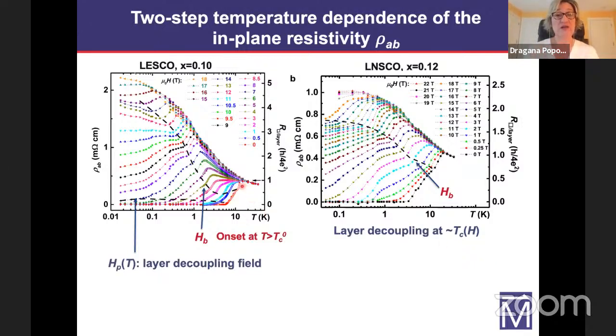Here we are showing curves that correspond to different magnetic fields. Temperature is on a log scale, so you can see the lower temperature behavior better. This dashed line connects these kinks, these initial drops of the in-plane resistivity, which is where the anisotropy is enhanced. And the dashed line here for this material shows where the layer decoupling field is. And as I said, in LNSCO, it basically coincides with the TC.